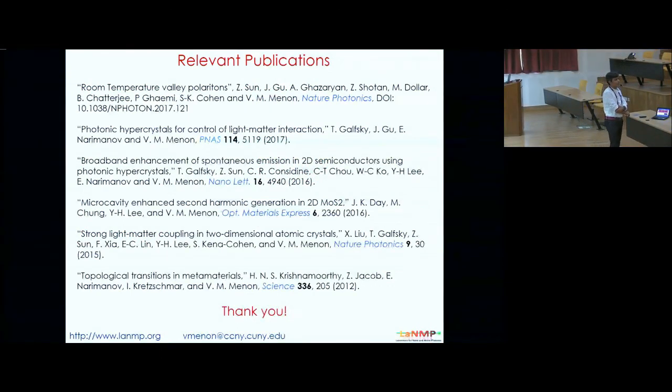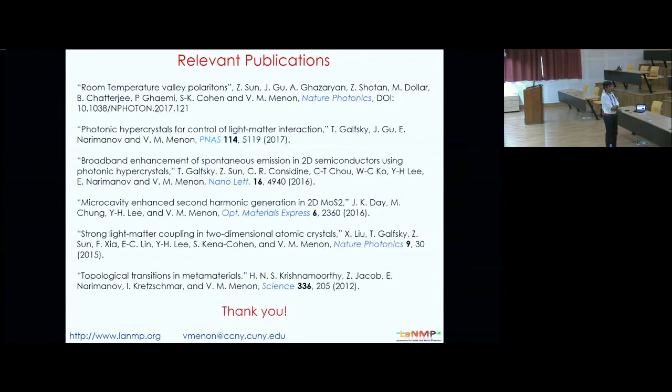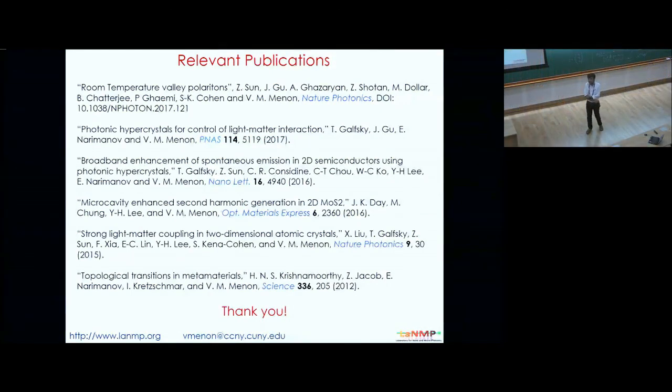Very, very nice, impressive. Is it known in boron nitride what these defects are? Are they single vacancies? So there is both. There are people who talk about this as being a boron vacancy or a boron substituted vacancy, and no one knows the answer. At least I haven't seen anyone saying it with confidence what it is. There's a lot of EPR work from the 70s on these systems. The other aspect I should mention is, unlike diamond, we have not seen any magnetic field response. We have tried it, and not so in most of the other groups either. So we don't know what kind of defect it is.